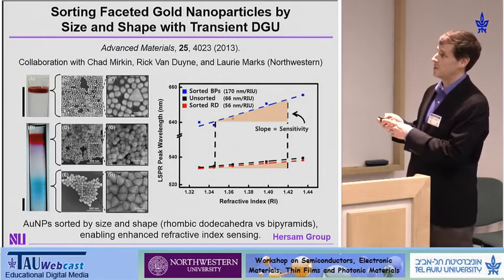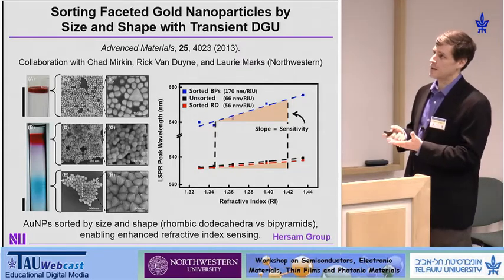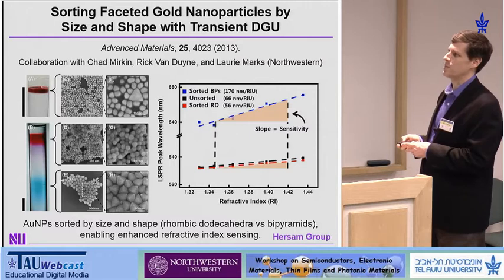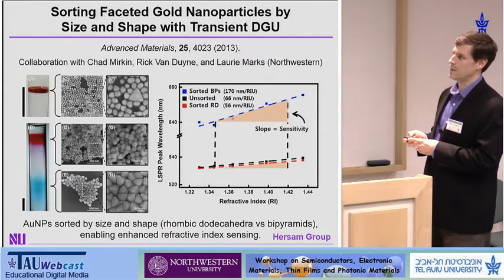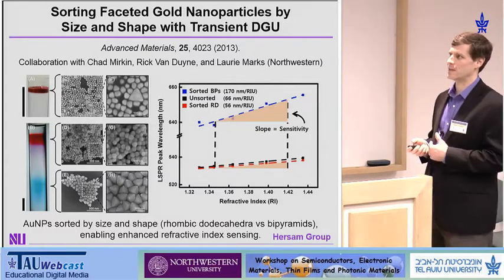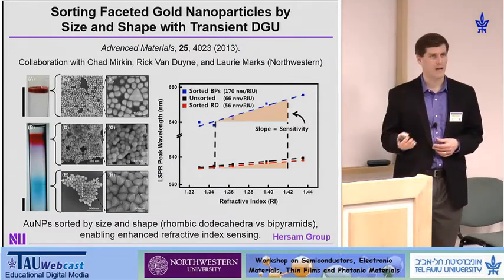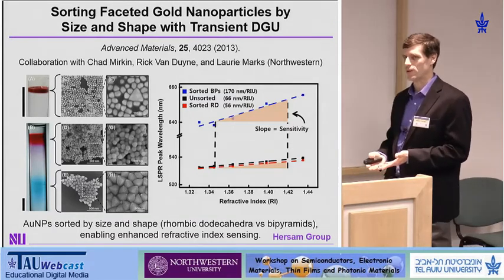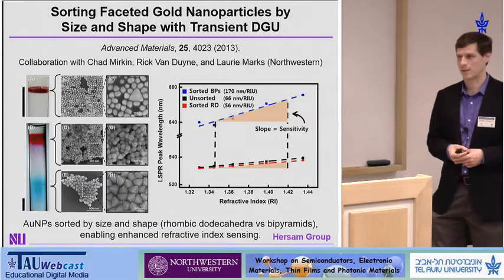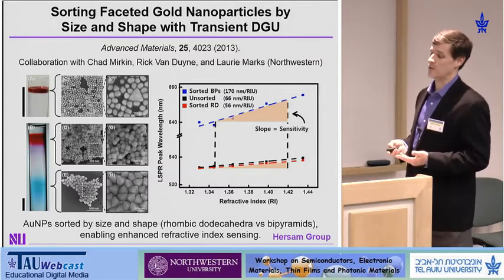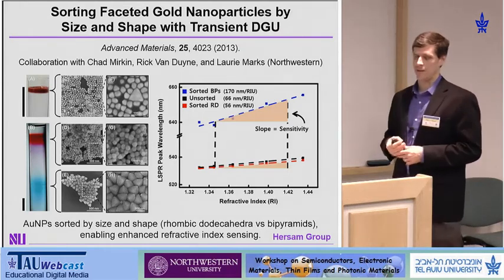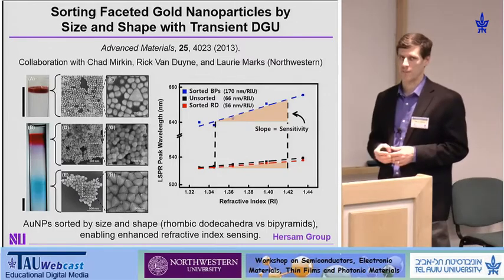This was a collaboration including Laurie Marks and others at Northwestern. Chad Mirkin's lab had developed a faceted gold nanoparticle solution, a mixture of rhombic dodecahedra and bipyramidal gold nanoparticles. Gold, unlike carbon, has a relatively high buoyant density. If you do DGU all the way to the isopicnic condition, all your particles sit at the bottom of the centrifuge tube because their density exceeds that of the highest density achievable in an aqueous solution. So in this case we use transient DGU — capturing the nanomaterials in their sedimentation regime — where sedimentation is driven most sensitively by molecular weight, so large particles sediment more quickly than small particles.